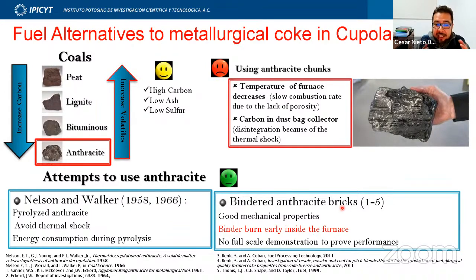But they started to notice that, okay, they have this solid briquette, and when they dump it or make a thermal treatment, the binder just burns and all the anthracite particles just shatter apart. And up to maybe 10 years ago, there wasn't a study that showed that these binder anthracite bricks can resist all the very hard conditions inside the cupola furnace. And here are some references about it.